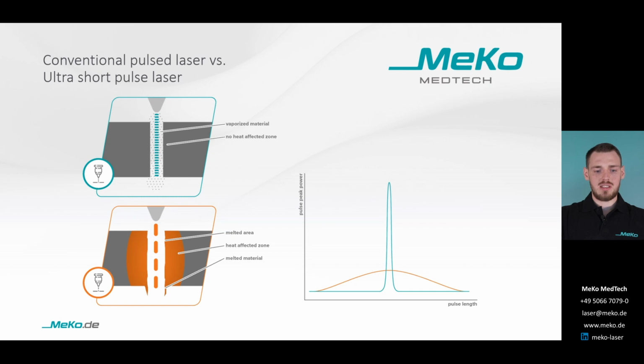And now when a laser pulse hits the material, it is not melted, it is directly converted from the solid to the gaseous phase. A single laser pulse ablates only a very, very small amount of material. So to cut through the material completely, the repetition rate needs to be very high and is usually in the range of several hundred kilohertz to several megahertz. This means that more than 100,000 pulses per second hit the material to generate a sufficiently large amount of material removal.